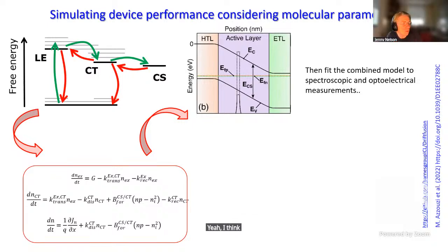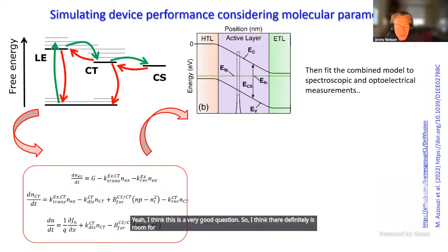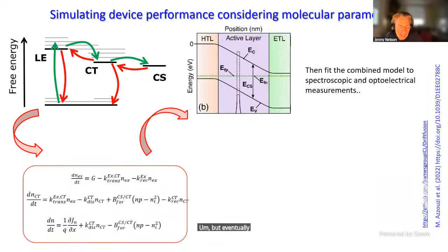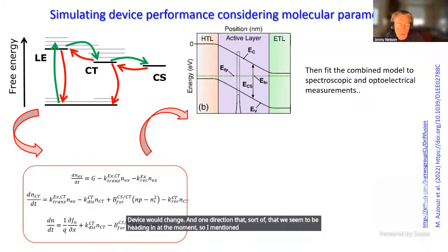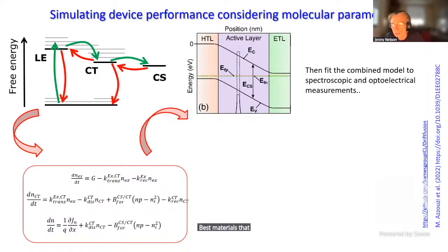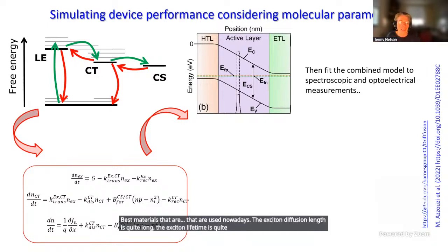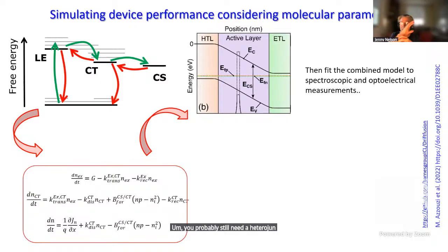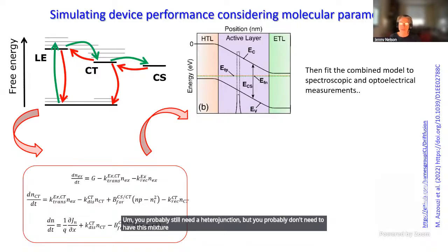Yeah, I think this is a very good question. So I think there definitely is room for improvement in the materials. But eventually, as the materials get better, then the optimum device would change. And one direction that we seem to be heading in at the moment, as I mentioned as we were going along, is that with the best materials that are used nowadays, the exciton diffusion length is quite long, the exciton lifetime is quite long. If we extend those to the conclusion, that would lead us to conclude that we don't need quite so much heterojunction. You probably still need a heterojunction, but you probably don't need to have such mixed materials.